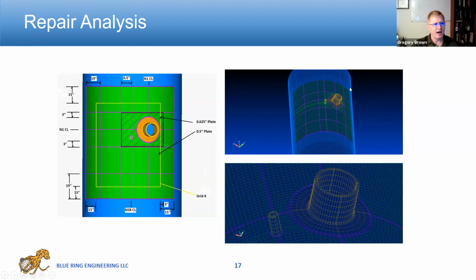We actually modified our corrosion model, our computer model, with the proposed repair, which you can see the various patch plates included. Turns out that repair was acceptable. So this was completed. The equipment successfully stayed in operation until a longer shutdown when they did a larger repair.